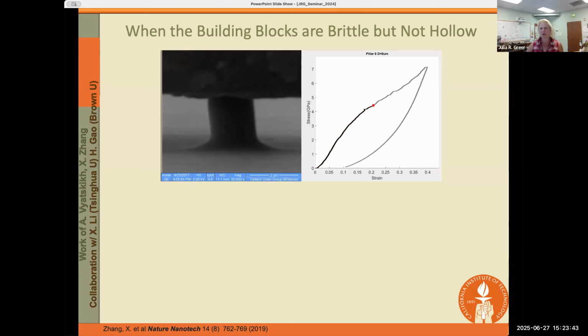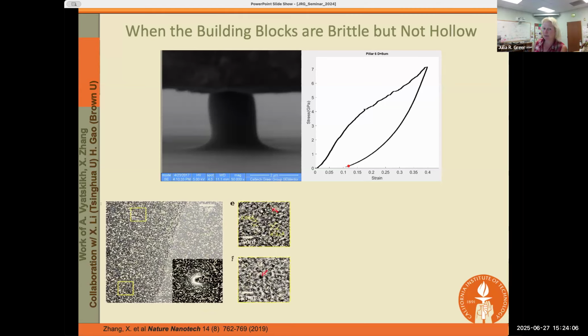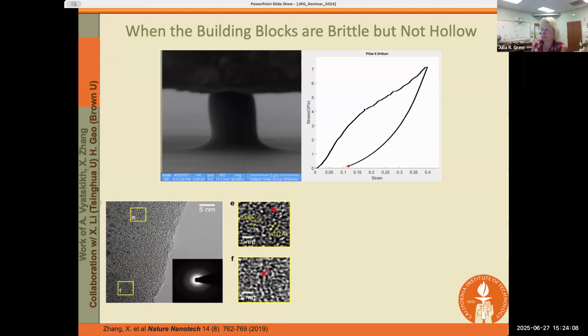So here's our pencil lead effectively, and we're compressing it. And this is very interesting. We're already at a stress of 5 GPa. This is gigapascals, right? So this is very, very high compressive stress. And what this guy is doing, it's bending, it's certainly not enjoying itself, but it is not fracturing. And this is very counterintuitive because we all know, of course, glassy carbon to be a very brittle material. So this is encouraging, right? So we are learning that maybe the monolithic building blocks are still going to work.